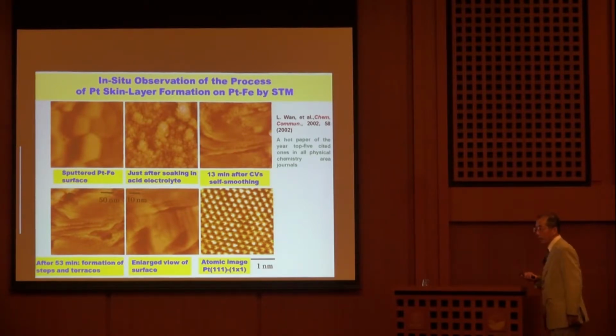That means the surface platinum atoms are rearranged on the surface and make a very well-packed surface protecting structure. It is not the skeleton structure, but the flat surface. And in spite of the formation of the platinum skin layer, just pure platinum skin layer, that property is completely different from the bulk platinum surface, as I already showed you.